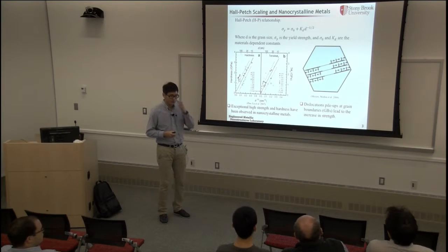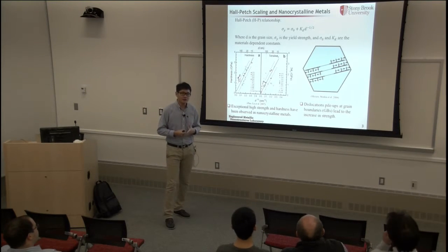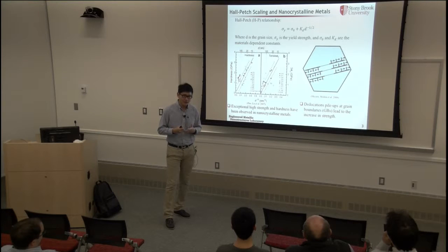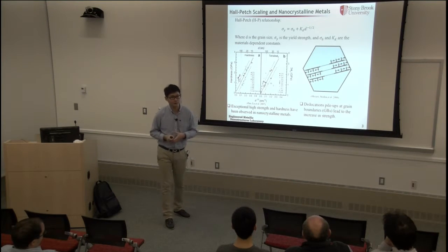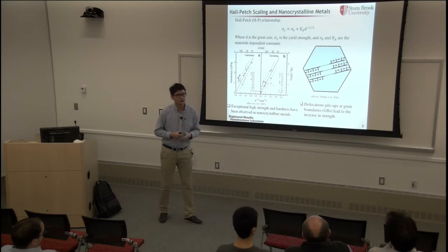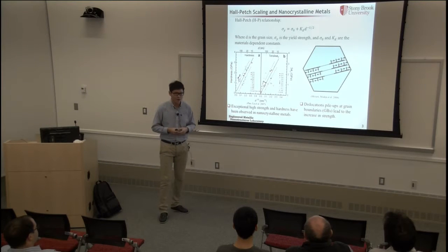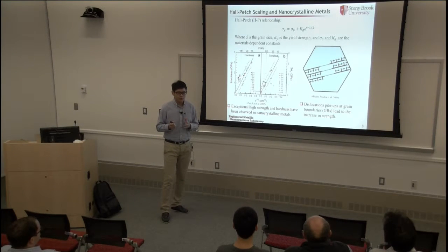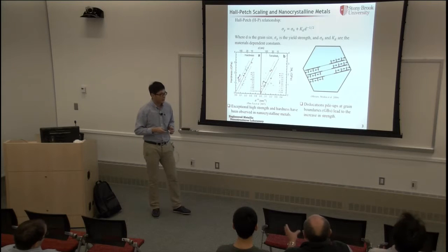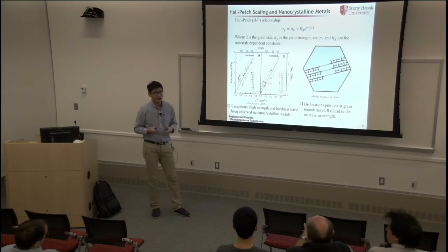What exactly is the yield strength? The yield strength is the criterion that tells whether the material is going to deform plastically rather than elastically. So there is a threshold, there's a criterion for that. Usually we use the slope, which is actually the Young's modulus, and we offset it by 0.2% strain and measure that yield strength in the stress-strain curve, for the transition between plastic and elastic.